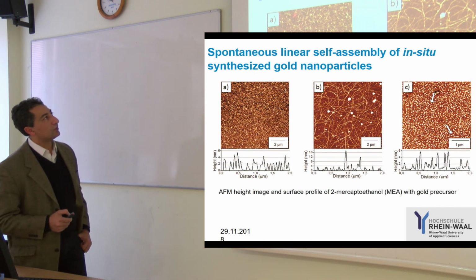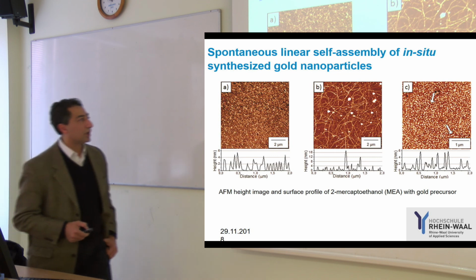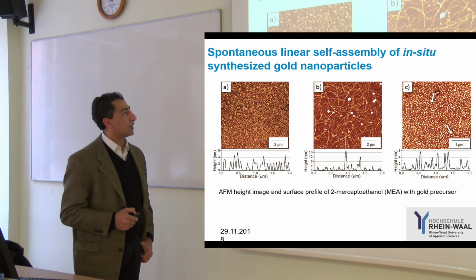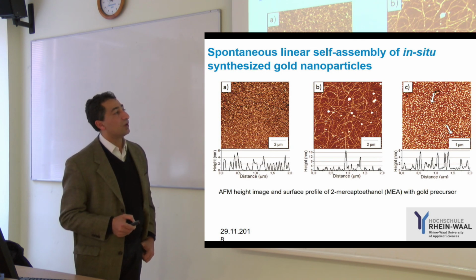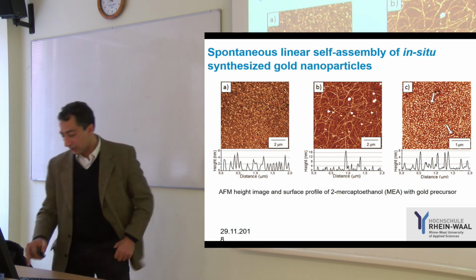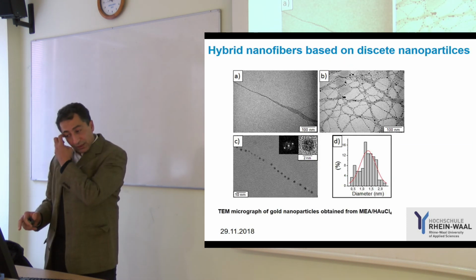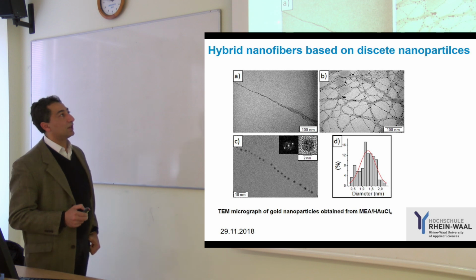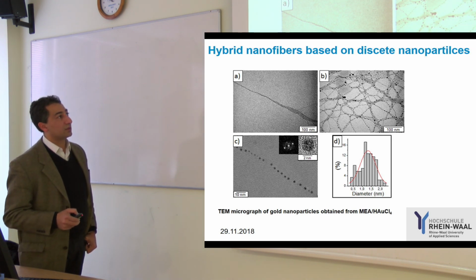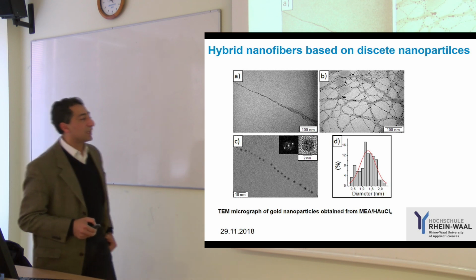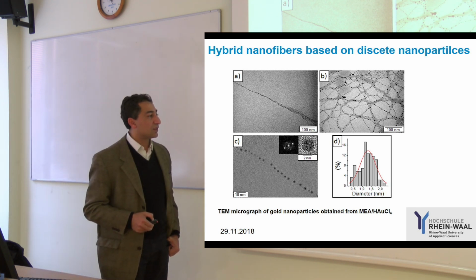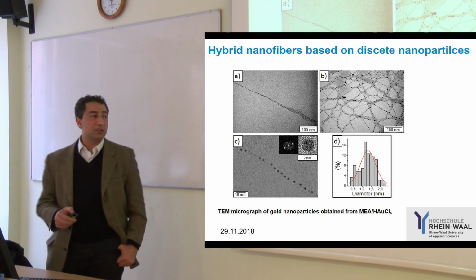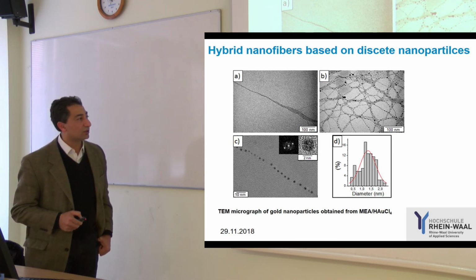Atomic force microscopy confirms that we can have spontaneous linear self-assembly by using the in situ approach, so that we have this fibril-like structure. We make different levels of structure, as you see from the atomic force image, so that you can have different architectures of this 1D structure, gold nanoparticles inside this very short surfactant. It is quite interesting that we have the fiber, where we align this very small surfactant in a fiber-like structure, but our aim is that we can adjust the distance between these building blocks, these inorganic building blocks, so that we have a well-defined structure in 1D. As you see, the distance is almost the same.